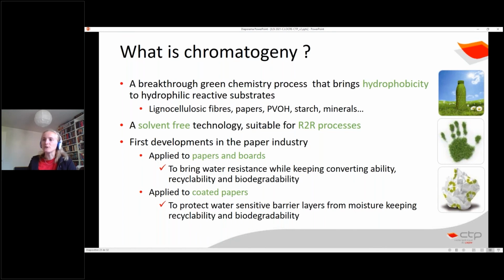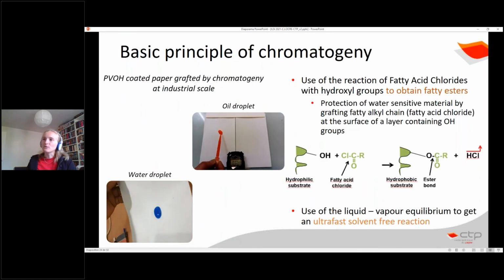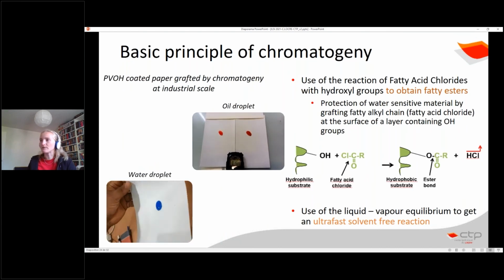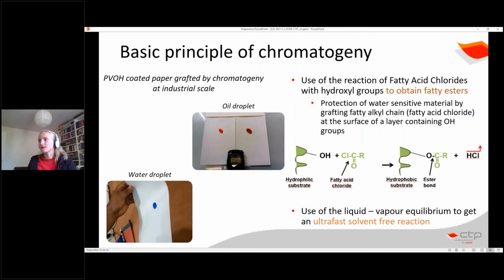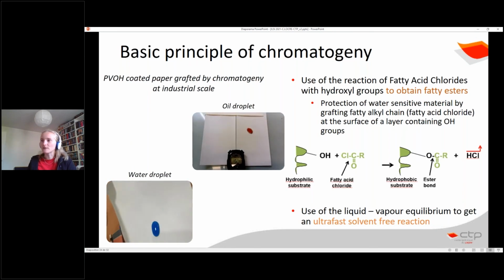And it can also be applied to coated papers, for example, polyvinyl alcohol coated paper, in order to protect the water-sensitive barrier. As you may know, polyvinyl alcohol is also a hydrophilic material, very soluble in water. So to protect this barrier from moisture, still keeping the recyclability and biodegradability performance of the material. So the basic principle of chromatogeny is to use the reaction of fatty acid chlorides with hydroxyl groups in order to obtain fatty esters that are grafted on the paper. So the idea is to protect water-sensitive material by grafting a fatty alkyl chain, so starting from a fatty acid chloride on the surface of a layer that contains a hydroxyl group.